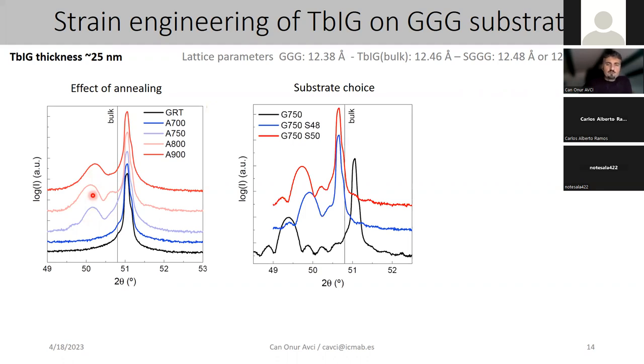So we could also do that. We realized that instead of annealing, so all these AAA mean annealed, we can also grow the films at higher temperature and get even better, more pronounced XRD peaks. So these are some attempts that we did on standard GGG at 750 degrees Celsius, the black one, and you see that there's a really nice XRD signal.